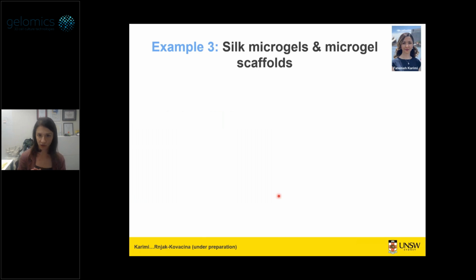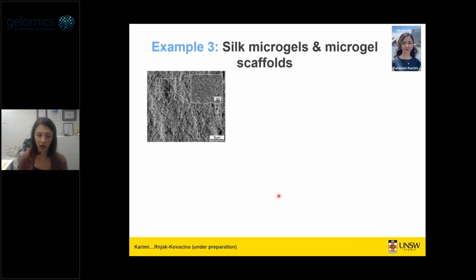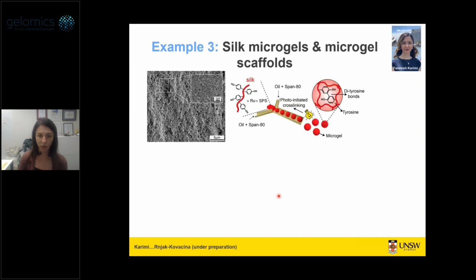My last two examples will be very quick. The silk microgel work is again related to this issue that we have, that we like lots of things about hydrogels, but they have nanoscale porosity, which makes it really hard for cells to actually modify them and change them and grow into them, and for vasculature to grow in. And so one way to solve that in the field is through microgels, creating microgels. So this is where you create tiny little hydrogel spheres. And in our case, we make them using a microfluidic device through phase separation, and we cross-link them using dityrosine cross-linking.